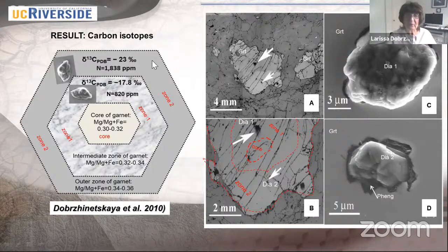So we decided to look if the diamond sitting in zone 1 and the diamond in zone 2 have similar carbon isotopes. The data show, when we summarize everything, that zone number 1 contained diamond with delta 13 of minus 17.8 and nitrogen 820 ppm. But diamond situated in the outer zone, zone number 2, has a minus 23 delta 13.